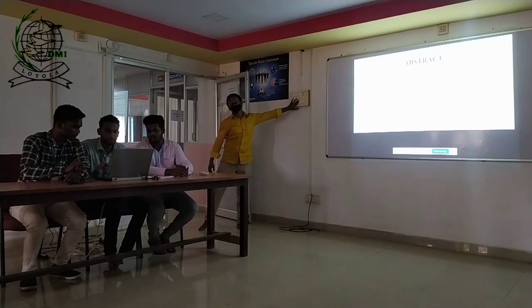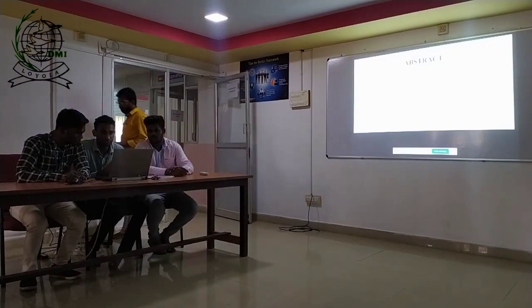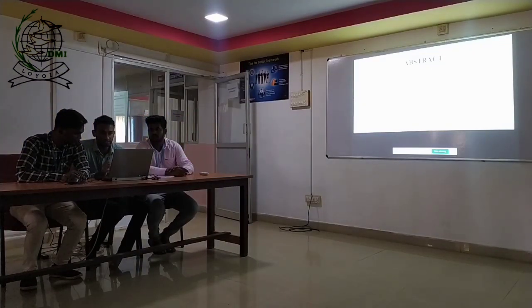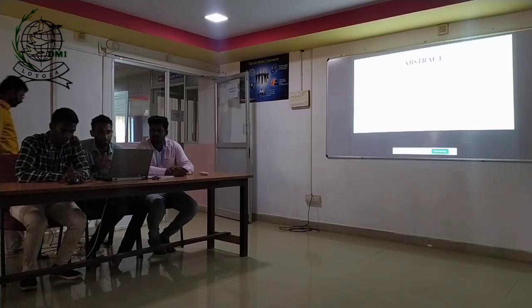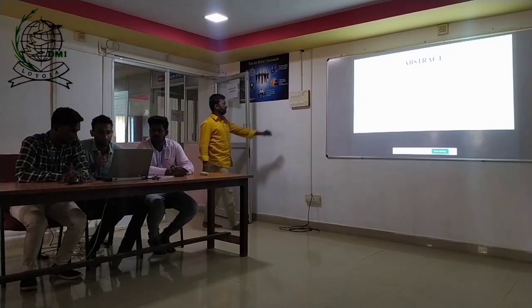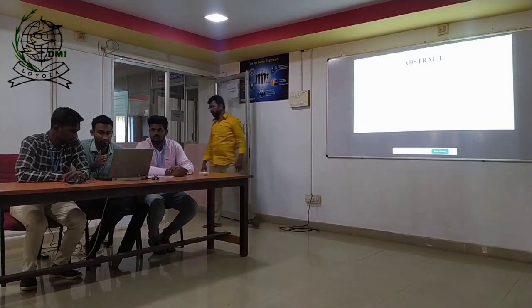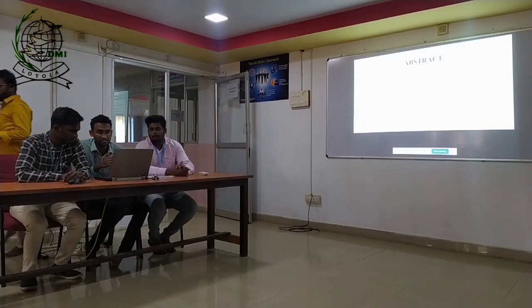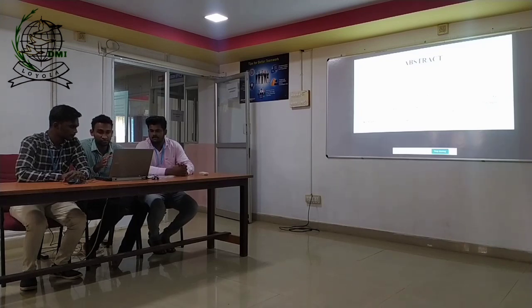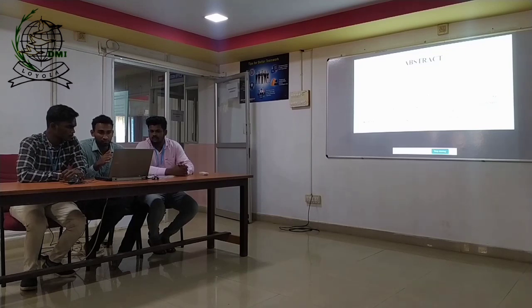Sir, to give an overview of what we have done: we have chosen AZ91 magnesium metal, and we have done stir casting. First we took readings with plain magnesium, that is 0%, and then we mixed boron carbide with it, and we did the same tests and took the same readings, and compared which one has a better ability or better standard in both. So the fractions which we chose were 0% and 3% of boron carbide for making this composite. All these things we did in a lab.